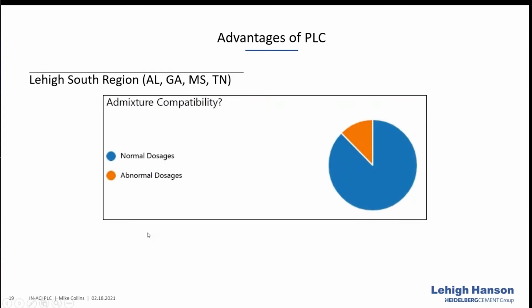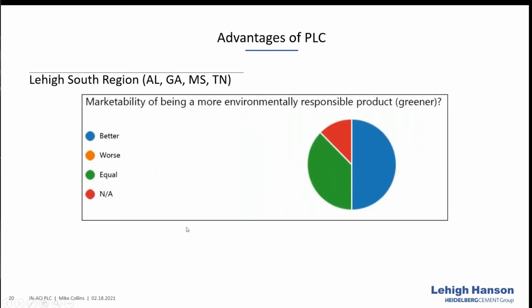Admixture compatibility: normal dosages for the vast majority, and just a hair there on abnormal dosages. I would even go as far as to say my guess would be that might be air entrainment, and we'll talk about that in just a bit. Typically, because of the fineness, there is a slight adjustment needed upwards in air entraining admixture, and once you dial that in, it locks in and it's not an issue. It's just an initial adjustment.